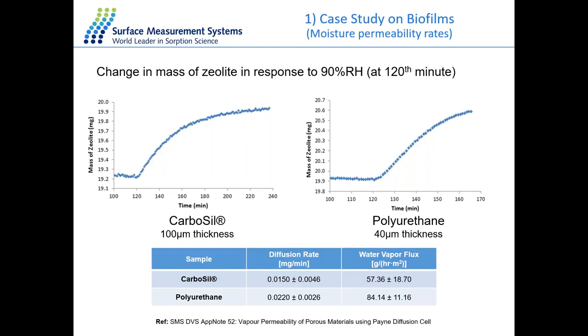So from the plot, the polyurethane film, which is the thinner film, shows faster kinetics. And also from the calculated results for diffusion and permeability, the polyurethane film has a larger value on both of the parameters. That means increasing the thickness of these polymer films will decrease the water transmission rate in this case. And we can also perform very similar experiments at different temperatures to study the temperature effect on the water diffusion with this film sample as well.